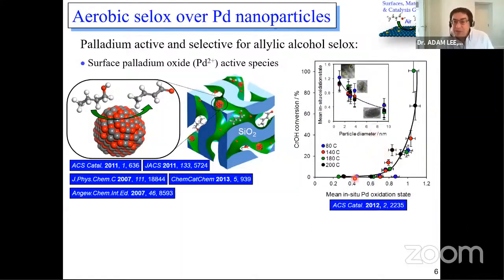I'm just showing you here some results of some XAFS, so some X-ray absorption measurements in situ, where we can track the degree of the alcohol conversion as a function of the oxidation state. And what you can see is that palladium oxide, high oxidation state, is very good for this catalytic transformation. So palladium is great for alcohols to aldehydes. What it cannot do is oxidize aldehydes to acids. So we can do step 1 of our cascade, but not step 2.